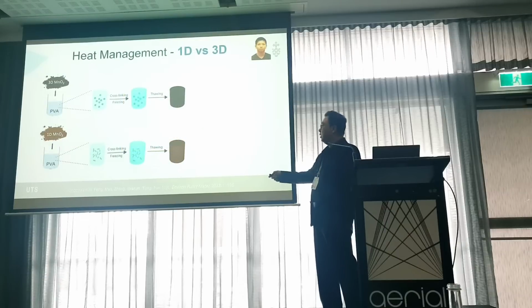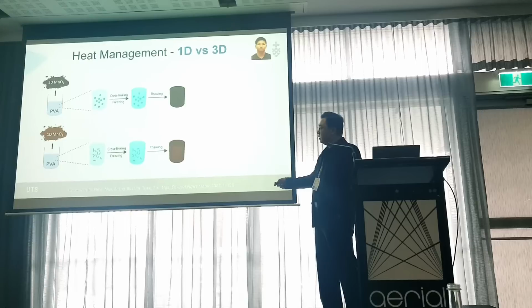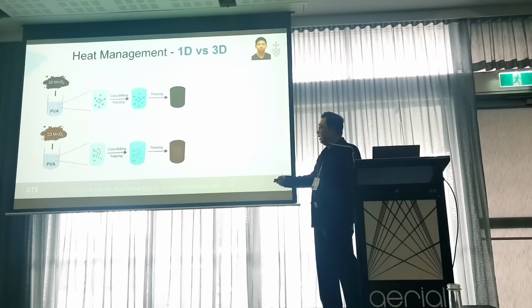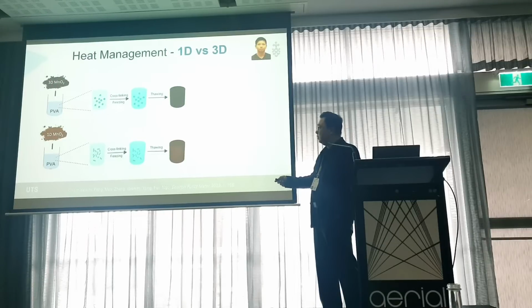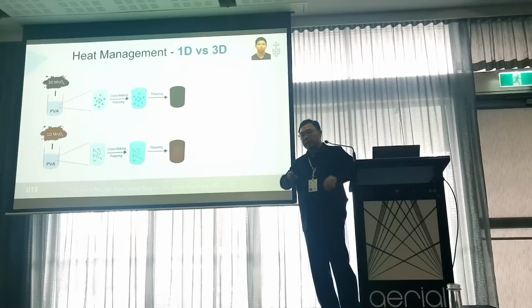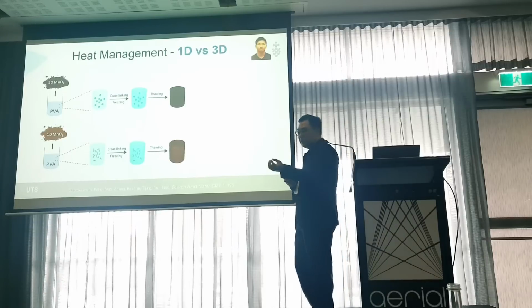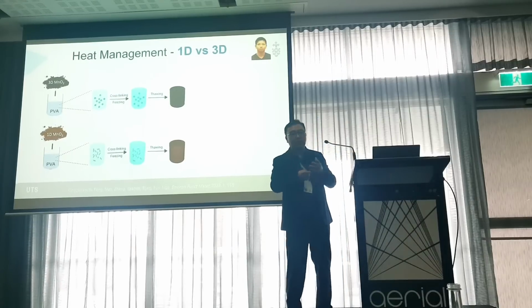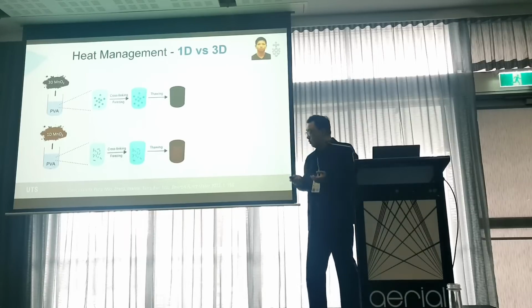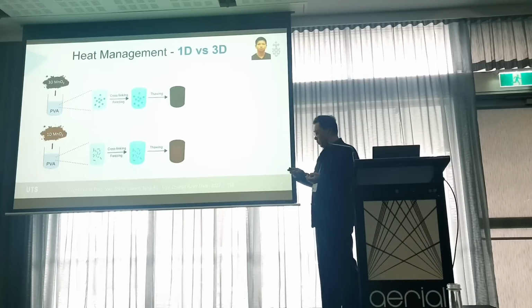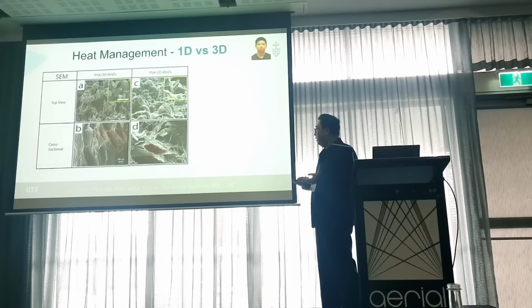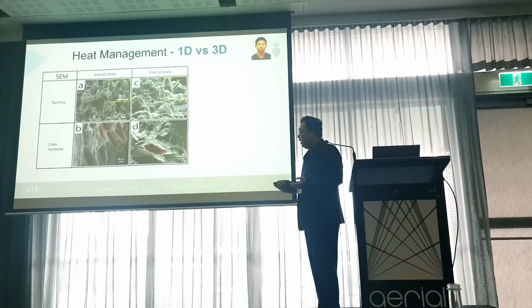And then we incorporate these photothermal materials into the polymer hydrogels. This PVA, polyvinyl alcohol solution, has 10% mass loading, and we introduce 1% of these photothermal materials. And I add the cross-linker. After cross-linking and freeze-thaw, we can successfully prepare two kinds of hydrogels containing different photothermal materials. And then we characterize them by SEM, for example.